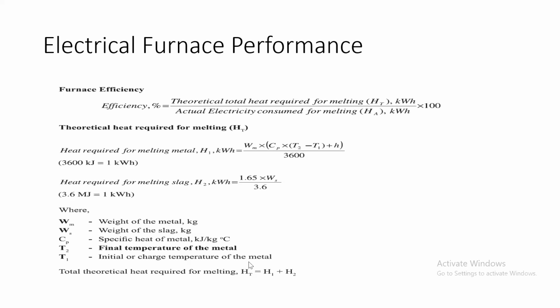So theoretical heat required for melting, HT, is equal to H1 plus H2. H1 is the heat required for actual melting of metal, and H2 is the heat required for melting the slag. The weight of the slag must be some 10% of the weight of the metal. Suppose you are melting 100 kg of steel, in that case the slag weight will be around 10 kg approximately. Now you can understand the concept of slag, which could not get burned fully and could not get melted. So that is how it can be 10%, and then the heat required for melting that slag is approximately 10% nearby. So ultimately that H2 can be found out by weight of slag into 0.45. Okay, is it clear? Shall we go ahead?